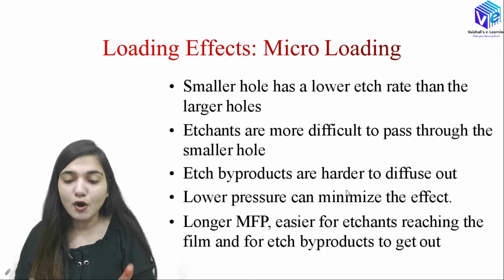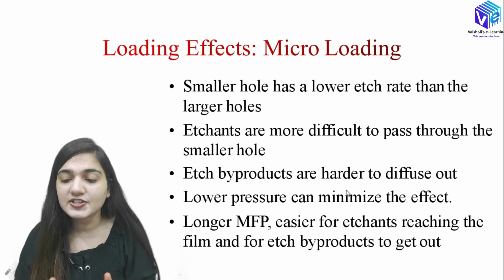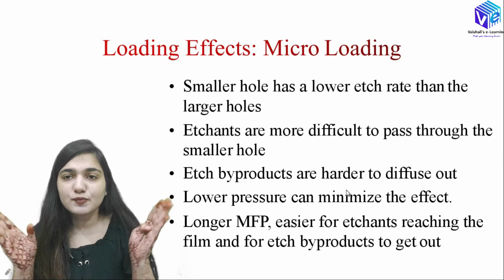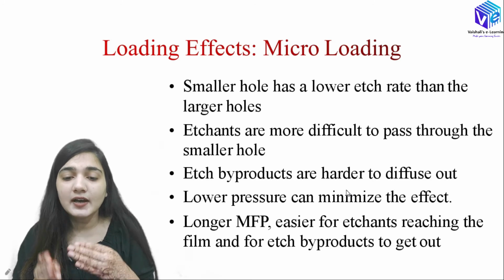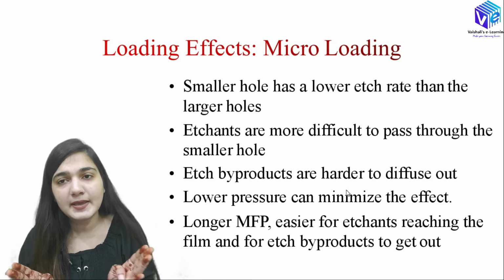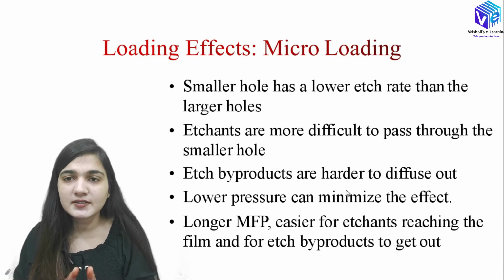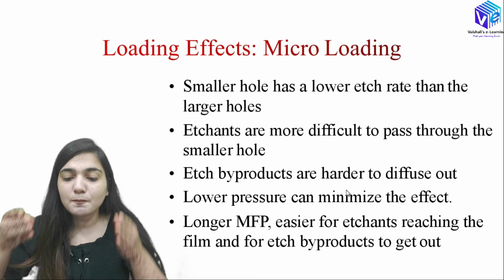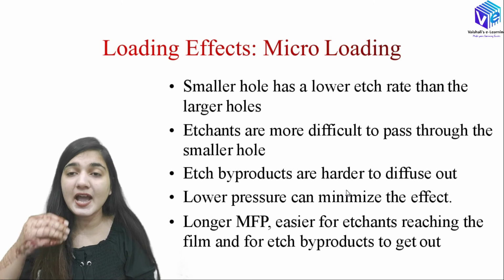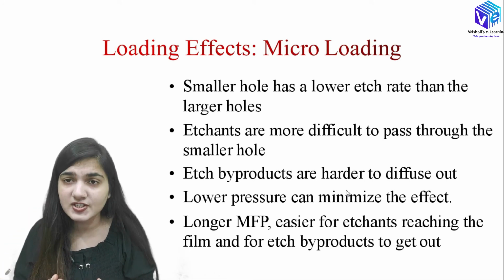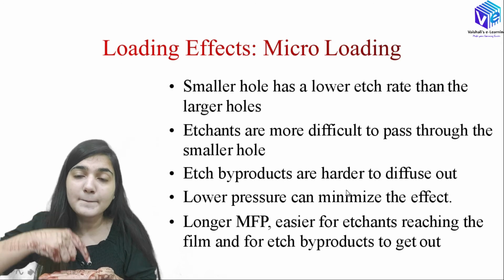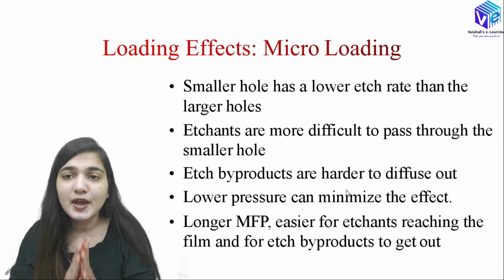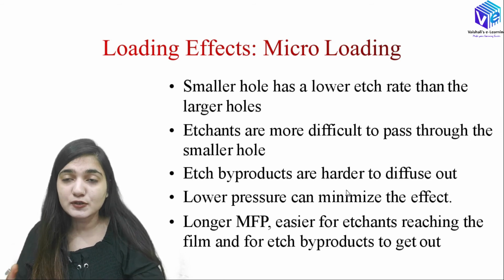So, if I have the smaller hole, it will be having the lower etch rate than the larger hole. So, it completely depends upon the feature size. The smaller the feature size, the higher the micro loading effect will be. Okay, I will be showing this with the help of a picture also. So etchants find it more difficult to pass through the smaller opening area, and this is the reason, if I have smaller feature size, the etchants cannot completely go inside, and this is the reason we will be having the bad profile over there. Okay, so etch byproducts are also harder to remove.